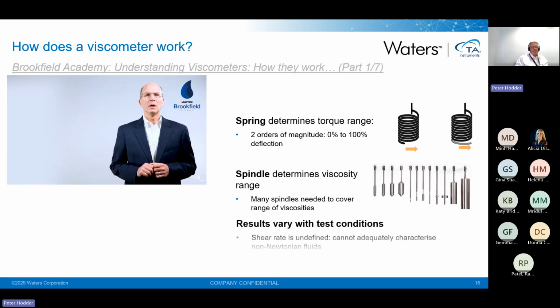So what we're highlighting there is that you have to choose the right base model to start off with, then play with the spindles to try and get a resistance that was in the torque range and try to avoid going over torque. And what wasn't mentioned in that video is, though you have a full 100% torque deflection, they don't recommend you work within the bottom 10% either. So they talk about torque ranges from 10% up to 100%. So that's a range of 90% to work with.